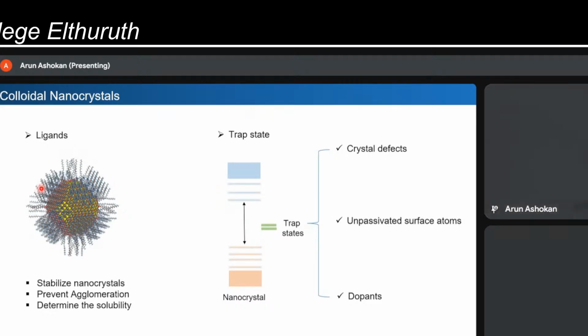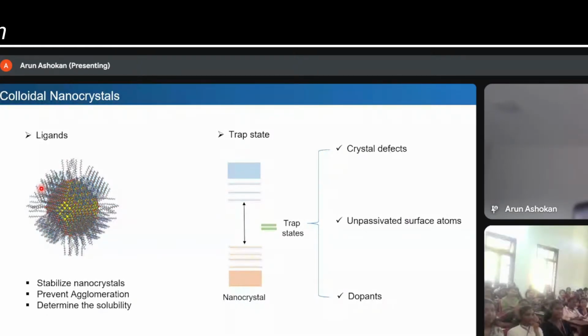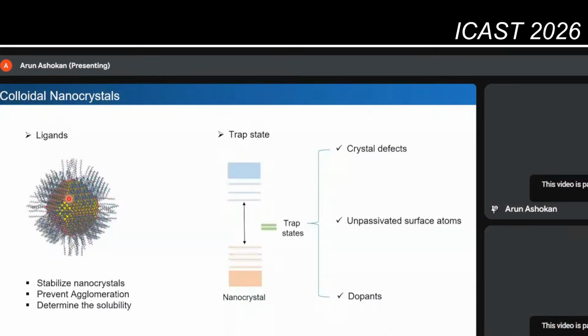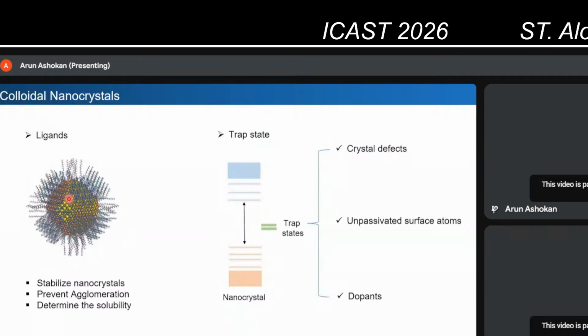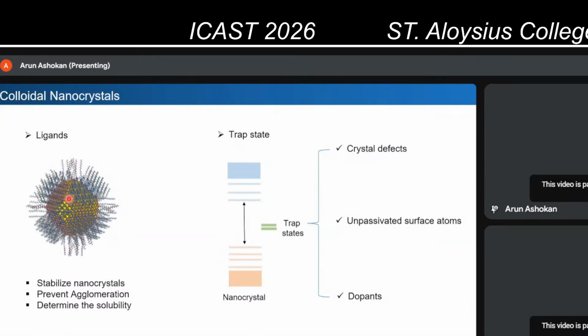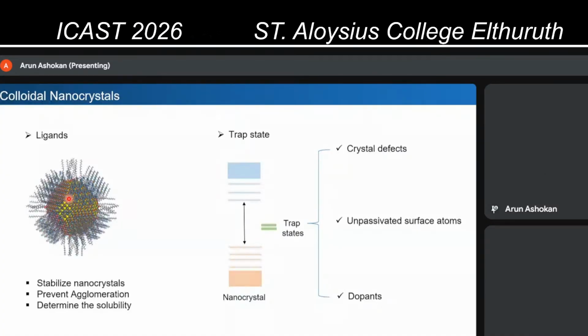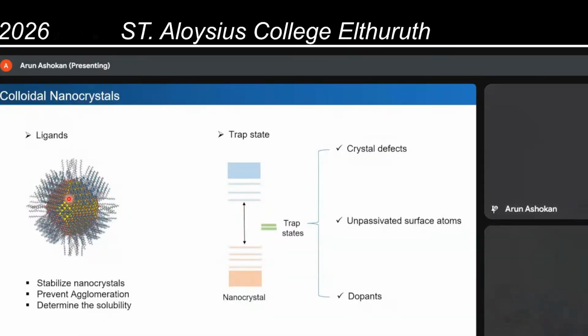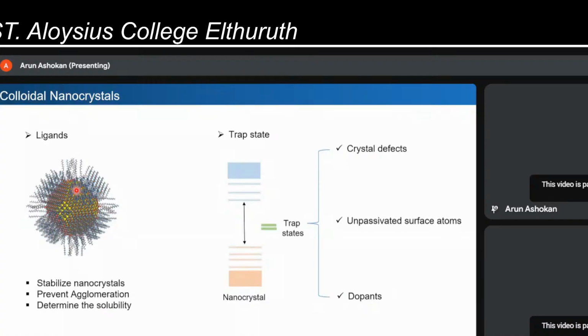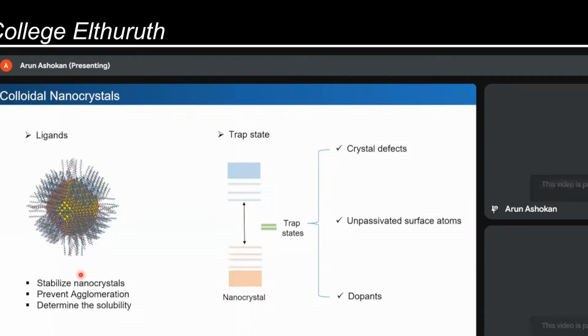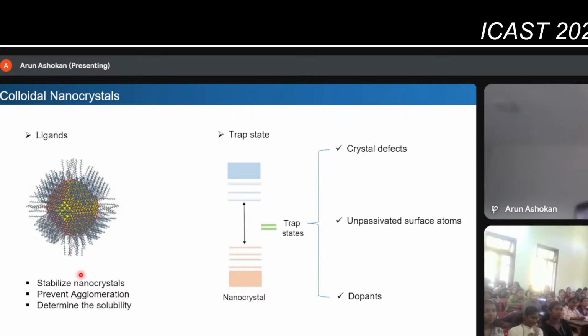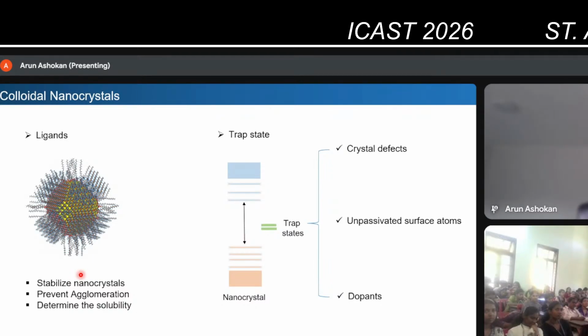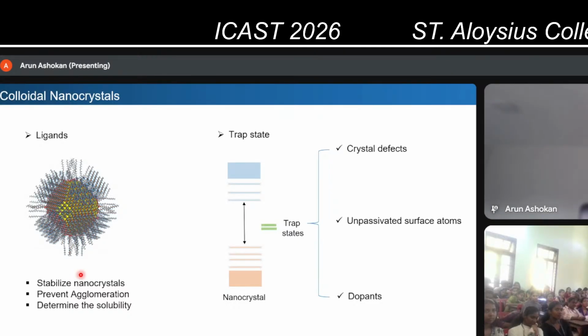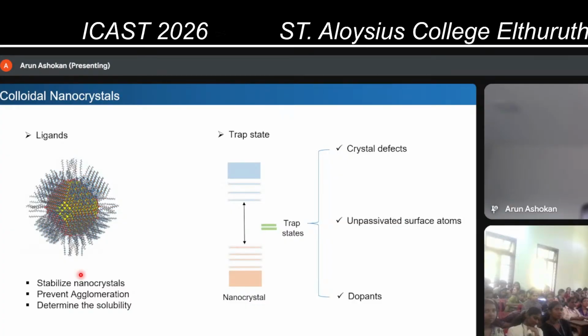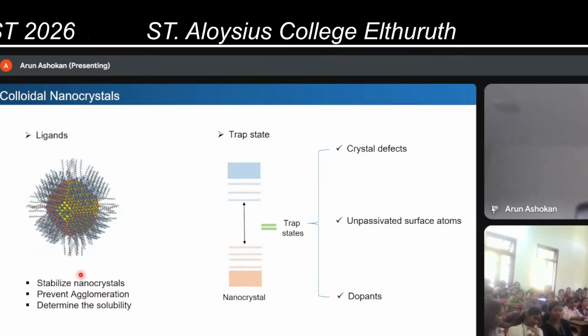Ligands are basically organic or inorganic moieties which stabilize the nanocrystals. Inside the nanocrystals, your atoms are coordinated to each other, but at the surface there will be uncoordinated atoms, so there will be a lot of energy. So you want to stabilize these nanocrystals. To stabilize them, we add some Lewis base, which can donate electron density to the uncoordinated atoms. So basically, ligands coordinate to the nanocrystals. They stabilize the nanocrystals, and also prevent aggregation between them. Without ligands, you have charges, and the nanocrystals will attract each other and aggregate. You don't want to aggregate the nanocrystals, and these ligands also determine the solubility of your nanocrystal. Suppose you want to dissolve in water, you can change the ligand in such a way that there will be hydrophilic interaction between the ligand and the water molecules.